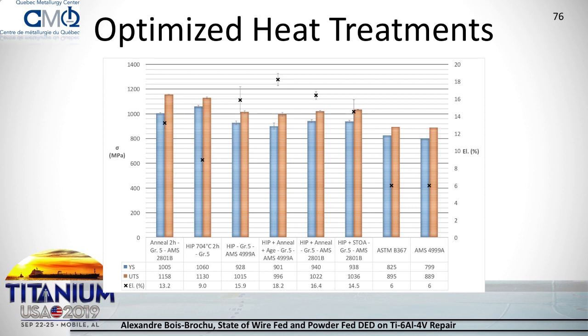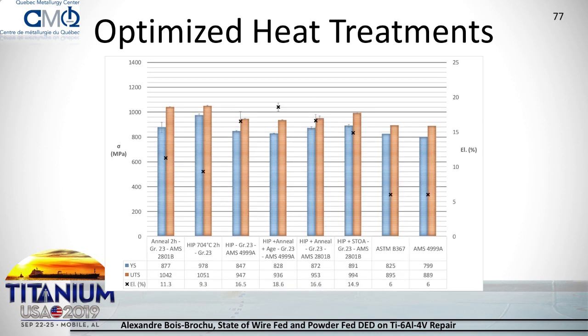Meanwhile, you have the same mechanical properties with only a HIP plus anneal or even a HIP cycle. And with grade 23, similar results can be observed. So the ideal heat treatment would be only to anneal at 704, since in this type of process, you'll have close to 100% density. In this case, it's higher than 99.9% density in the produced part. So only annealing at 704 will produce very good mechanical properties.